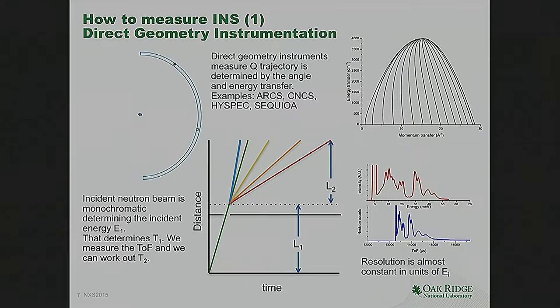So the resolution, as a consequence of the design of this instrument, is constant in units of the incident energy. The incident energy is the energy that I fix with my monochromating device, in this case a chopper. So the spectrum essentially looks the same way whether you look at it in energy or in time of flight.